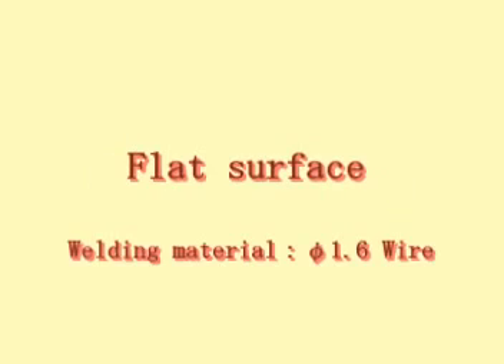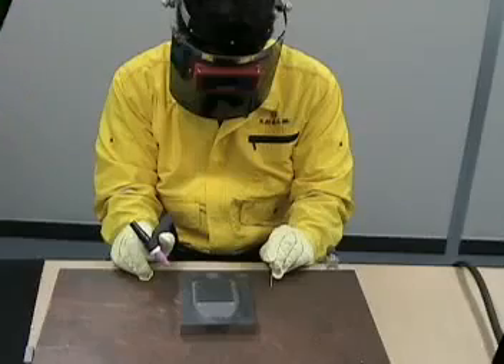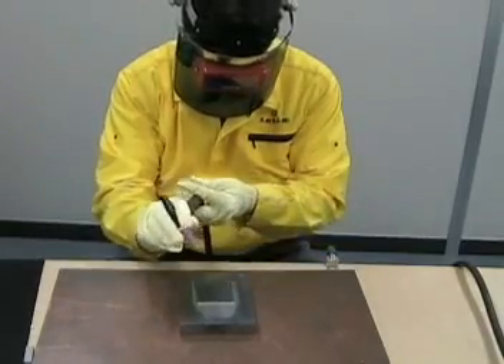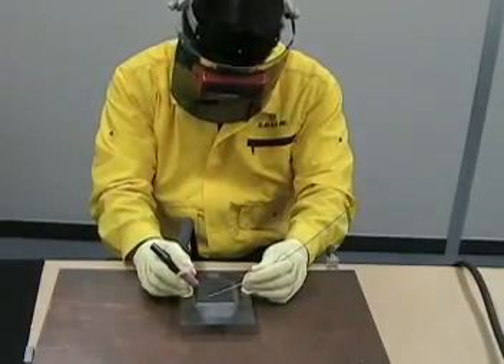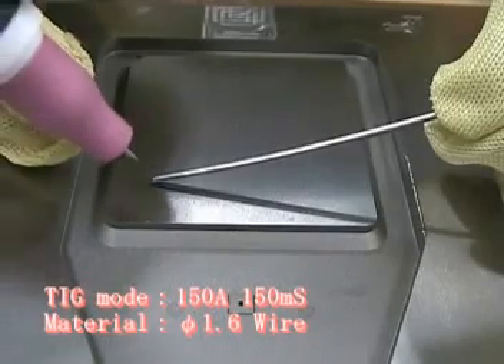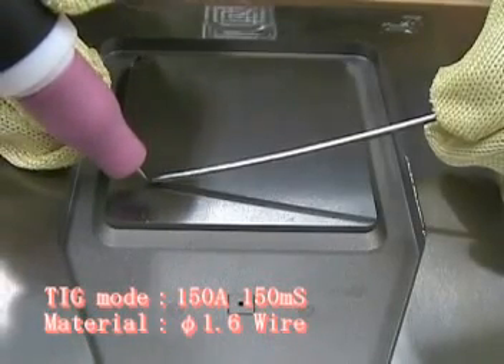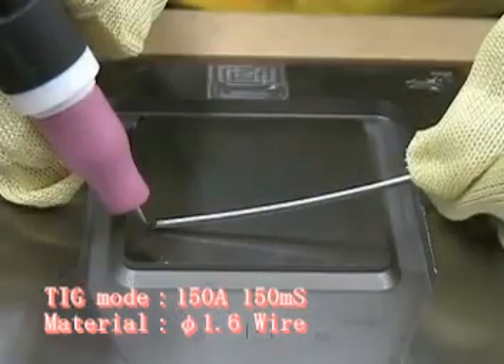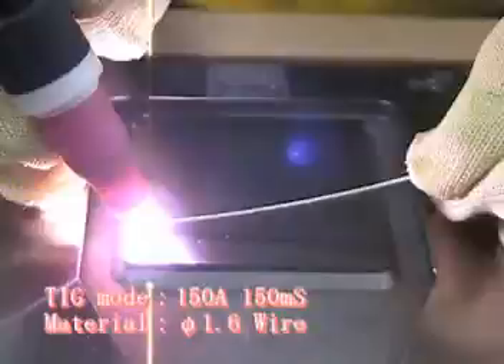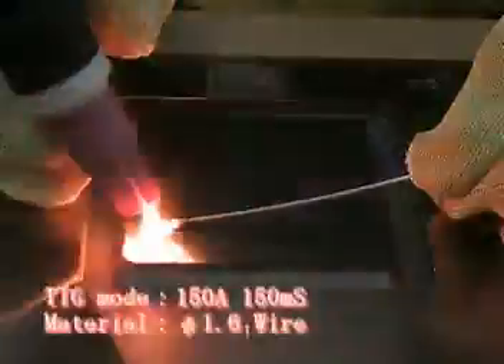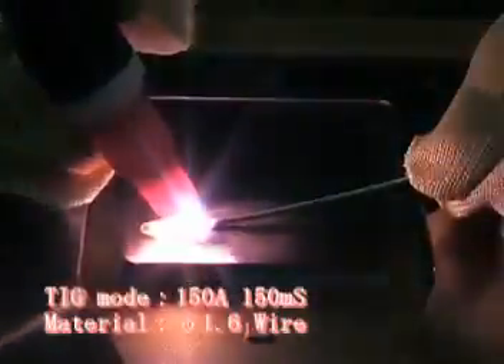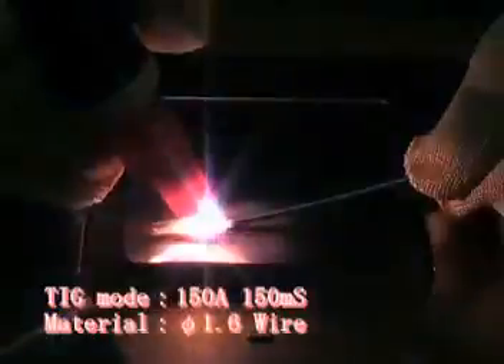Next, clad by welding. Use heat-resistant gloves like this for high-power welding. When you use welding materials more than one piece, do not fix them on the target points. Weld by holding the materials in your hand. Use the continuous mode and push the welding material a little into the base material during welding.